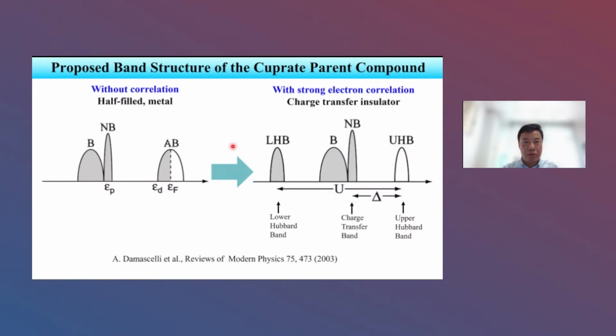Also, as we know, for cuprate superconductors, the parent compound is actually half-filled. So without correlation, it would be a metal. But because of the strong electron correlation, this band splits into an upper band and a lower band by the on-site Coulomb repulsion U. And in cuprate superconductors, in the middle between the UHB and the LHB, there is another band derived from oxygen. So actually the real gap is between the charge transfer band and the upper band. So it's the delta. That's why, strictly speaking, the parent compound of high-temperature superconductors should be a charge transfer insulator, not a Mott insulator. But loosely speaking, we still call it a Mott insulator.